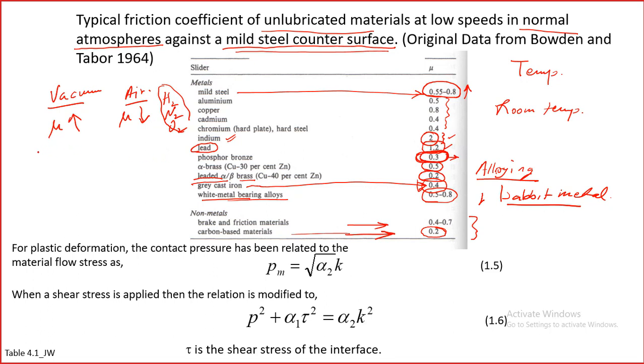And this happens because in vacuum we have less contamination. Every surface has some contamination in the form of oxide or some hydrocarbon. This contamination tends to give you a low coefficient of friction. So the friction that we measure is actually not from the true metal inside. For example, if I talk about Fe, it is not iron, but rather the iron oxide which is on the top. And it happens for all materials. But when we apply vacuum, it is possible that oxides will be taken away, and therefore there will be fresh metal to metal contact, or at least whatever contamination was on the surface has been taken away, and therefore there is a very high adhesive interaction and they adhere to each other.